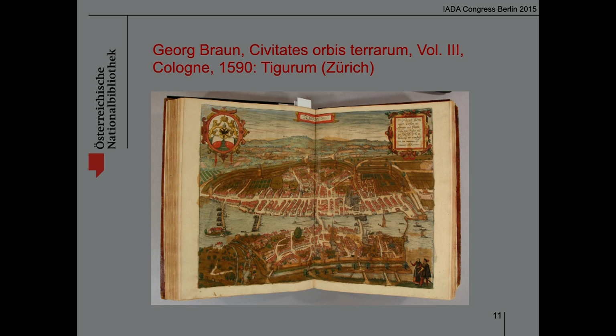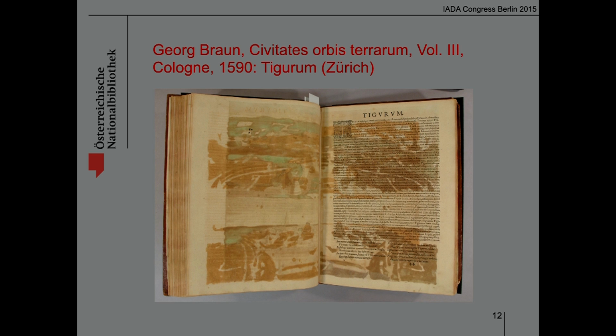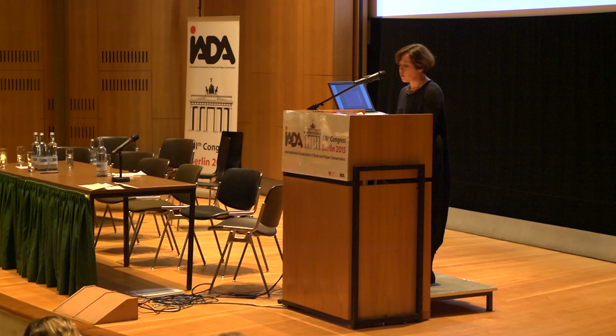Many, but not all, green areas have changed to brown. In most cases, the green coloration has migrated to the verso, in its brown discolored form. There are many pages where brown discoloration has also migrated to adjacent pages. At some point, the volumes were exposed to high humidity, which has resulted in water stains and mold spots. The degradation caused by copper-containing pigments is especially pronounced in volumes 2 and 3.